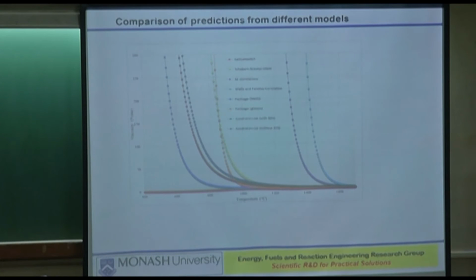One model is telling you it will give a very low viscosity, meaning really smoothly flowing, at 600. And then another one is predicting that you will have to go to about 1500. And the other ones all lie in between. We know very well that at 600 nothing happens. We generate ash at 600 running. So which one is correct?